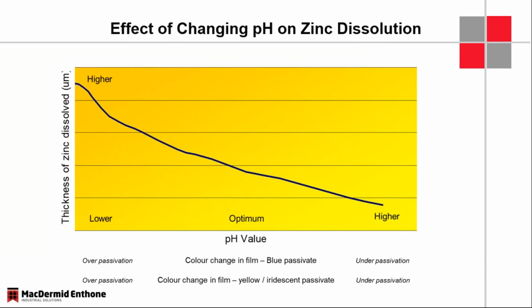Similarly with the zinc dissolution, and zinc dissolution we will get to in a little while, because that is extremely important with trivalent Passivates. So you can see that the lower the pH, you're going to be under passivated. The higher pH, you're going to be over passivated, and you're also going to dissolve less zinc at the higher pH. So if you're able to run a process at a higher pH level, it is certainly recommended, because you're going to dissolve less zinc, which is a contaminant.